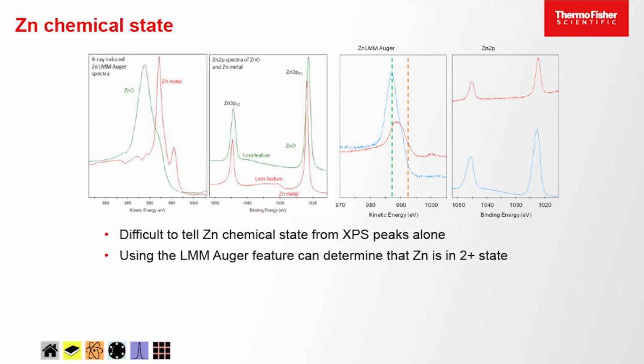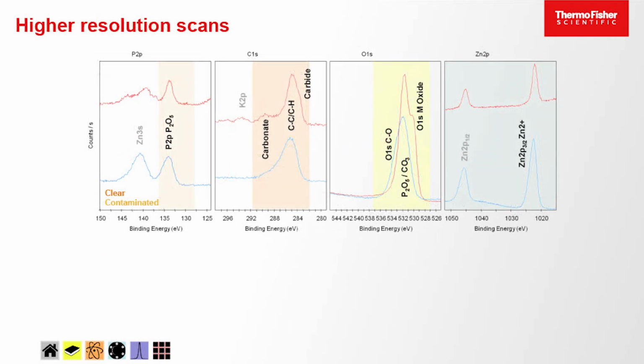Now the core level peaks for zinc, for the metal and the oxide, James just showed you a range of chemical shifts for carbon and for iron. Unfortunately for zinc, it doesn't change peak position at all when you go from metallic zinc to zinc 2+, which you'd have in zinc oxide and other zinc compounds. However, we do see quite a big shift with this Auger feature. You can see over here in the reference data, zinc oxide looks like the green, zinc metal looks like the red. And so by comparing between our contaminated and uncontaminated surfaces, we can see that the zinc is in a 2+ state.